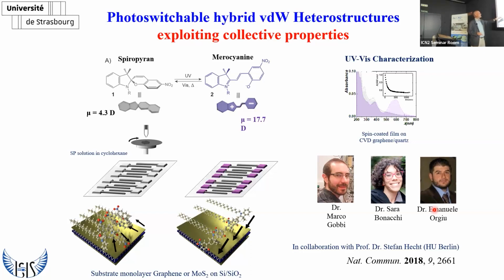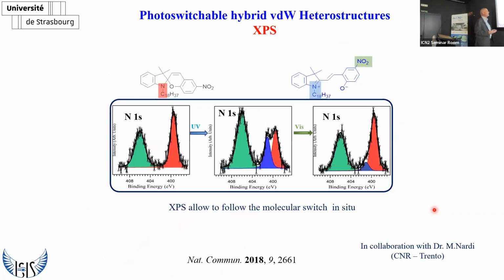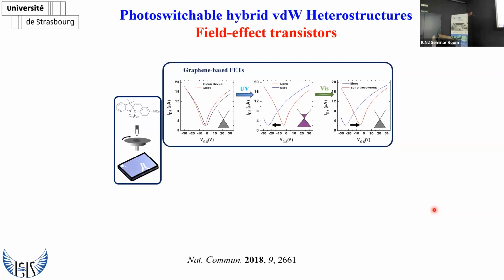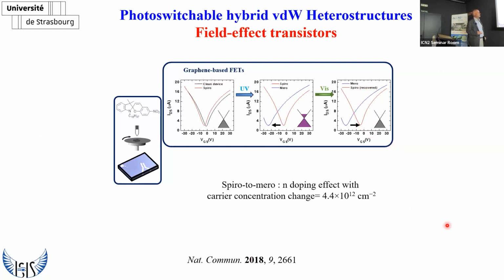Now this can be used if the substrate is MoS2 or graphene. You can use this to dope and undope the 2D materials. Well, I can skip the characterization. You can see how in the transistor we start in black with a clean device, this is the case of graphene, and then in red with a small n-doping effect upon physisorption of the spiro. And upon illumination with UV light, we trigger isomerization from spiro to mero. We have a major n-doping effect going to the blue curve, which is totally reversible upon visible light illumination.